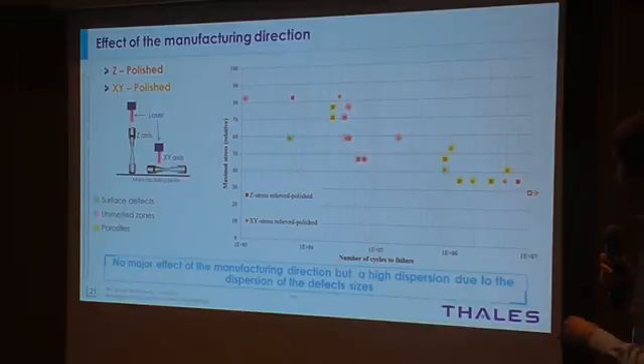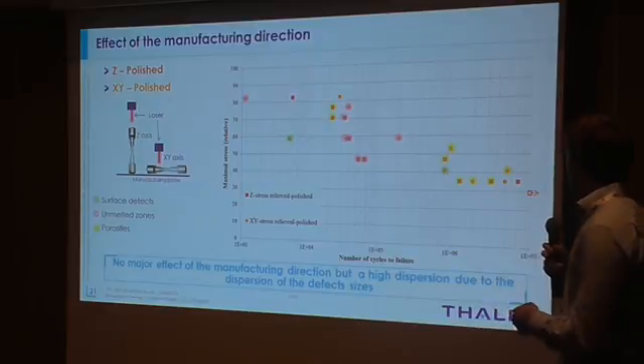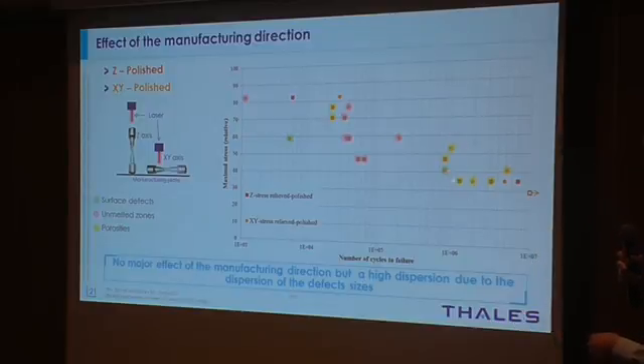And with the three type of defects mentioned earlier, we try to map the results. So at high number of cycles, the specimens almost always fail from porosities. At lower number of cycles, they often fail from unmelted zones, and we can see that dispersion is higher in this zone, and it can be explained by the fact that the geometries and the size of the unmelted zones are very different between the specimens, and implies a higher dispersion.